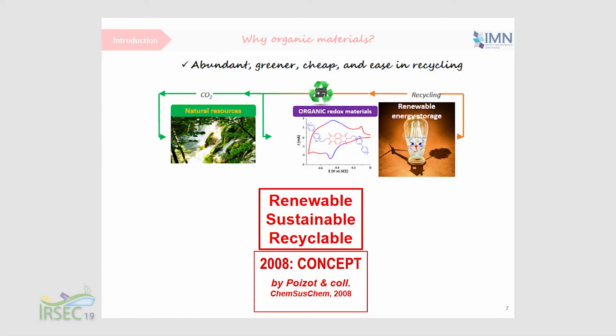Also, after the end of life of the battery, it's quite easy to recycle these materials by low temperature combustion techniques. And the CO2 which is released will be absorbed again by plants through photosynthesis. Of course, this is theoretical, but you can see that this closes the CO2 loop, and we can say that the CO2 cycle has a virtuous carbon footprint. So in short, organic batteries should be renewable, sustainable, recyclable. And this concept has been proposed by Poizot more than 10 years ago in a paper published in ChemSusChem.